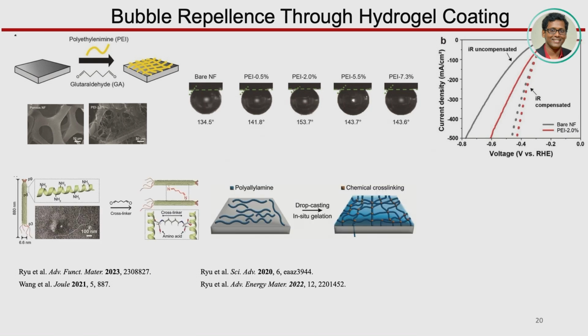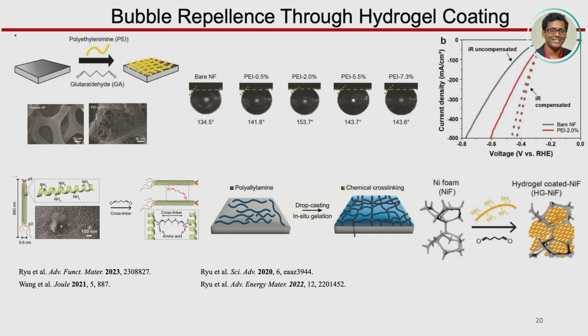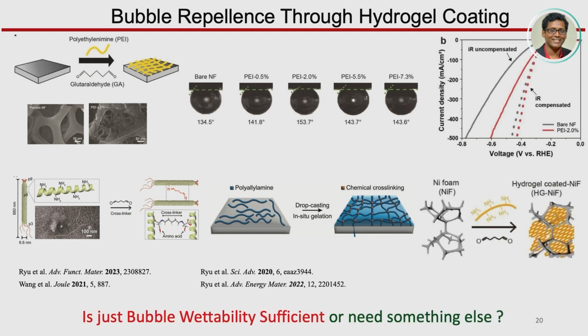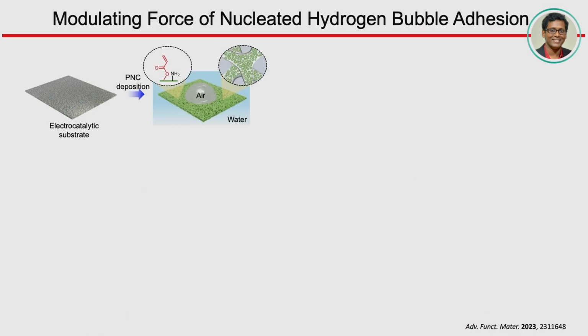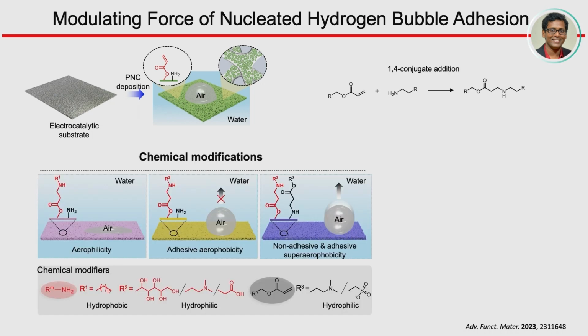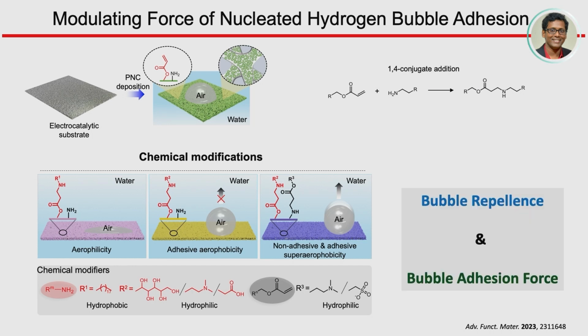And since then, different types of materials have been deposited, whether virus or other polymers or even bacterial fibrils and all. But none of these has the ability to directly modulate an important property, that is bubble adhesion. It can only play with the bubble wettability. So then we thought, let's go with this particular design where we can grow a multilayer construction of these nanocomplexes on this nickel foam and play with the chemistry to associate different kinds of functional groups so that we can play with both bubble repellency and bubble adhesion. And we remained quite successful here.